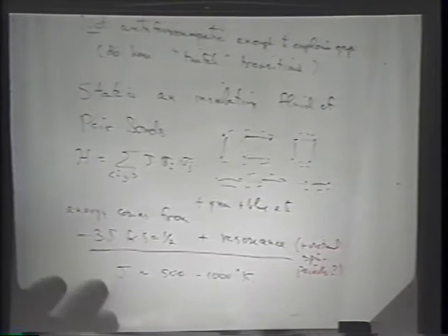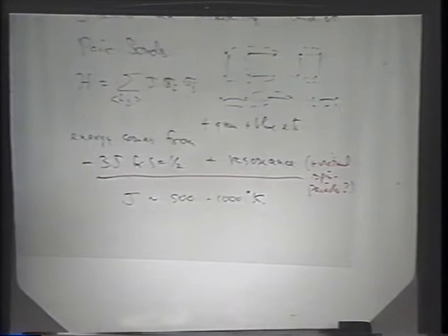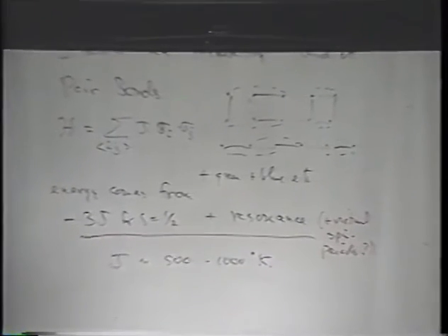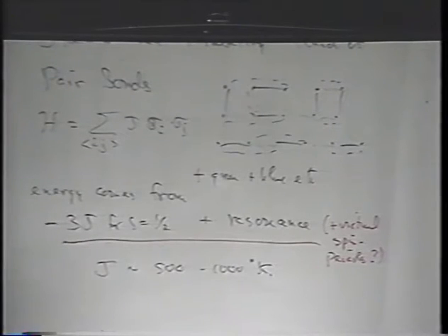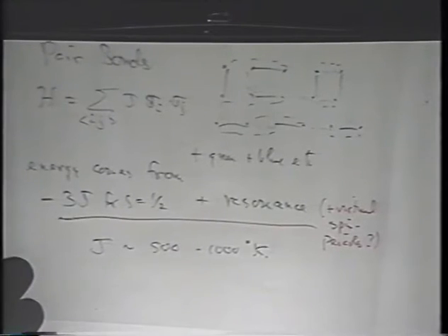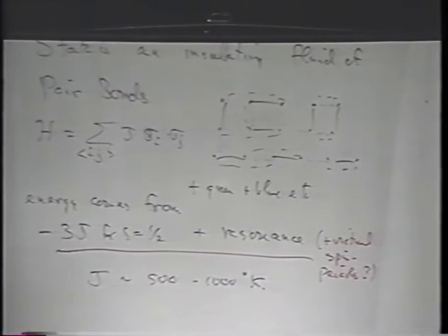There are various ideas that have been proposed to explain these having gaps. None of them really wash very well. They are all pretty clearly not antiferromagnetic, or not antiferromagnetic enough to explain the gap. So we suggested this very strange state, which is an insulating liquid, an insulating fluid of pair bonds between the different atoms. In other words, of singlet pairs made up of spins on the different atoms. We put one electron per atom. We keep one electron per atom to make it an insulator. But then we allow the spins to move around at will, as though they were binding themselves together in singlet pairs.